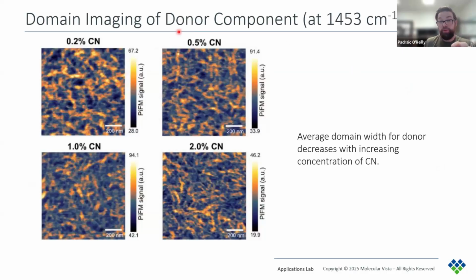Now, from these PiFM images that are taken at 1453, again, which highlight the donor component, we see that as you increase the concentration of CN, the domain sizes decrease. So, for example, the top left here is showing the lowest concentration. The bottom right is showing the highest. You can see a clear change in these domain sizes.